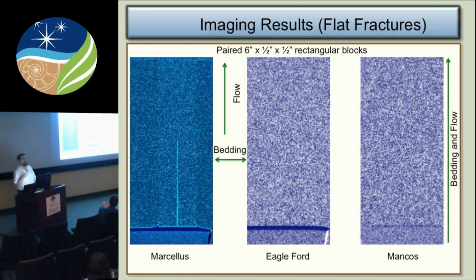Now, I'm going to skip this in part, but show you a little bit of it. This is uptake in the Marcellus Shale. I'll start in a minute. And what you'll see is pretty much there's not a whole lot of permeability in the Marcellus. As this goes up, this is about 3 inches. You can see this gets a little bit wider with time. But pretty much over the time scale we're looking at, in the Marcellus, things are very strongly confined to the fracture itself. However, and I'm going to skip to Eagleford for now just because of time.